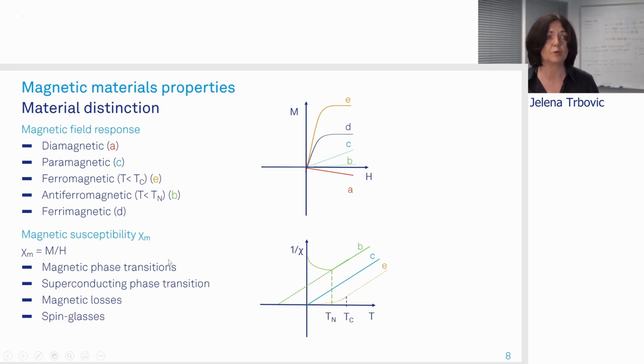In addition to that, we also want to measure the magnetic susceptibility, especially as a function of temperature, to see the Curie-Weiss law and understand where the critical points are at which these materials lose or gain their magnetic properties, and we have the onset of spontaneous magnetization. So we can study magnetic phase transitions, we can study superconducting phase transitions, and also magnetic losses and complicated systems such as spin glasses.